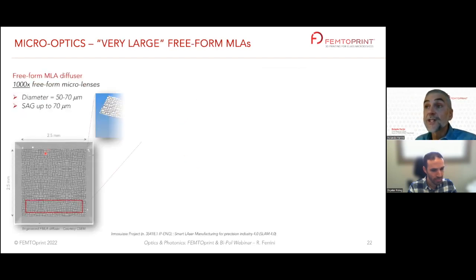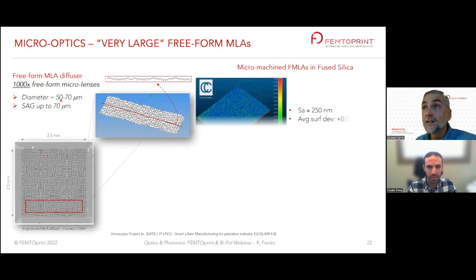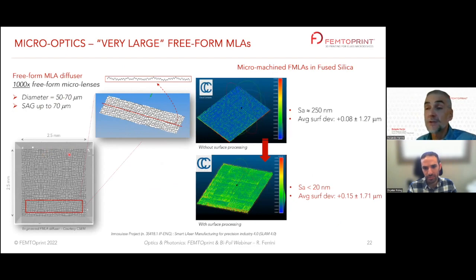But we have already done, for example, high sag microlens arrays. This is the same sample I showed you before, totally fully freeform. The lenslets had diameters of 50, 70 microns, an order of magnitude less than what I showed you before. You see also an order of magnitude higher in terms of number of lenslets, and the sag is up to 70 microns. You see that the ratio is not anymore 2:1.